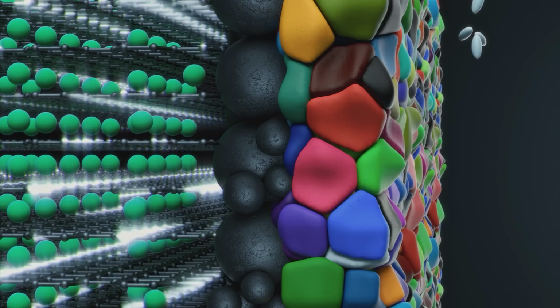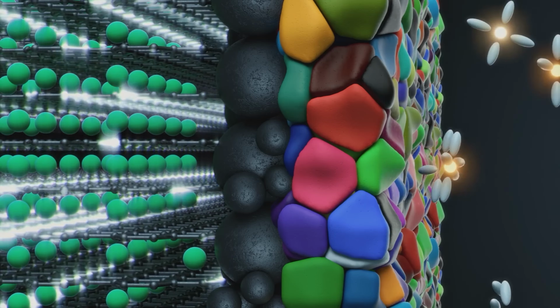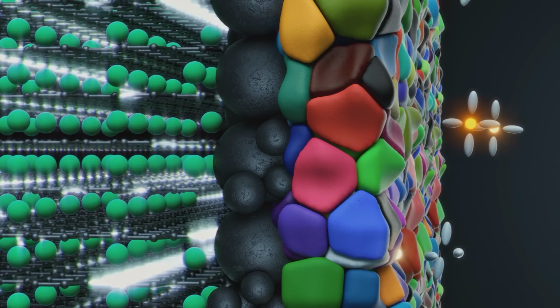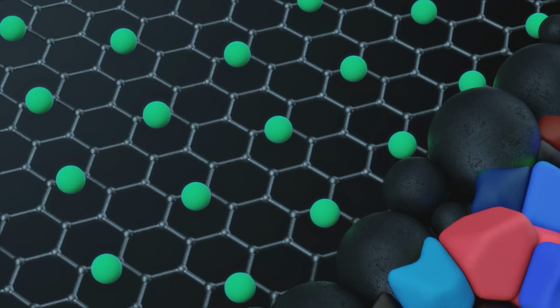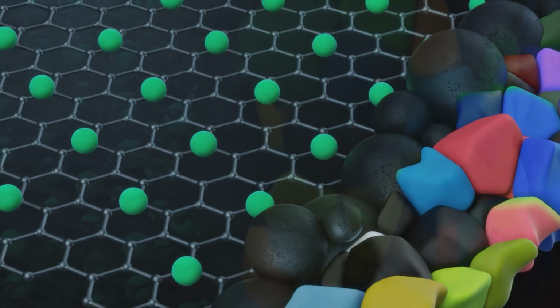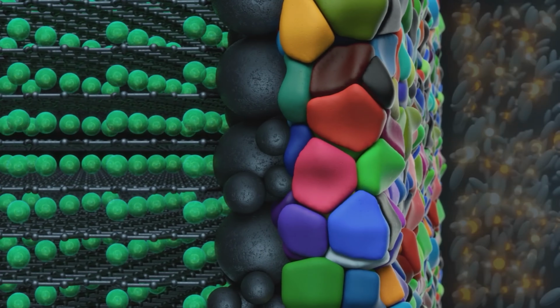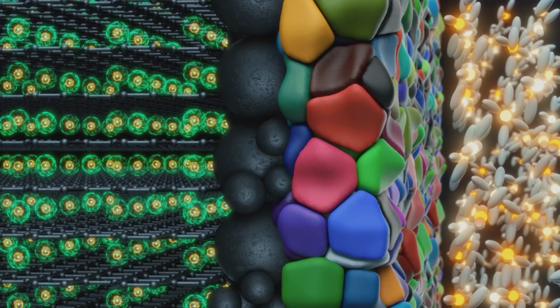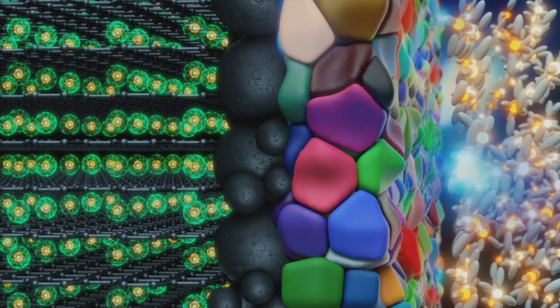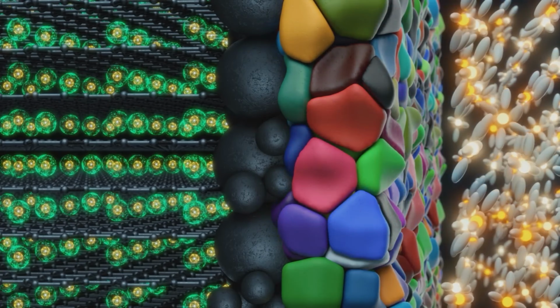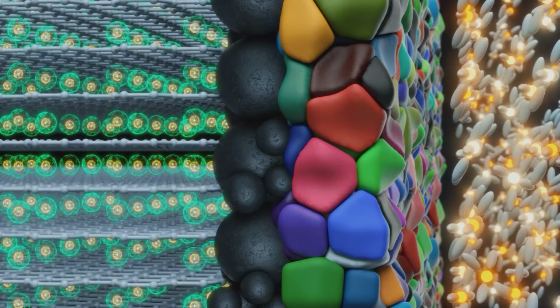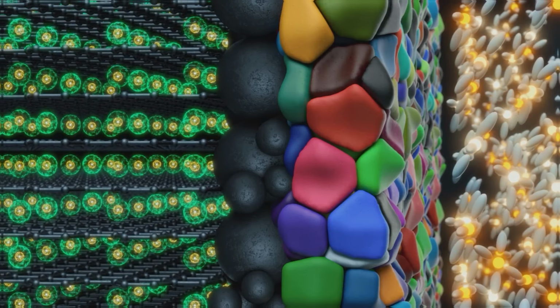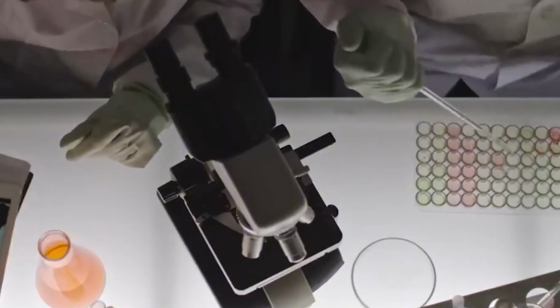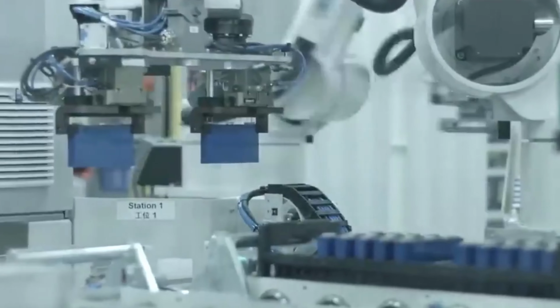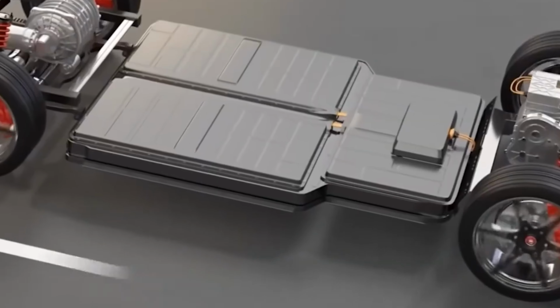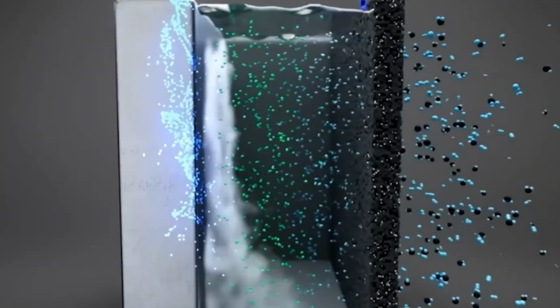Getting there is difficult because the oxygen in air arrives as a molecule of 2 atoms bonded together. Lithium peroxide keeps both atoms, so it is simply easier to make, while lithium oxide requires breaking that bond. The team managed it with a catalyst on the cathode and the composite electrolyte underneath, and even lithium peroxide that does form appears to convert. The researchers say they are not entirely certain why. The most promising battery chemistry beyond lithium-ion works better than its designers can fully explain.